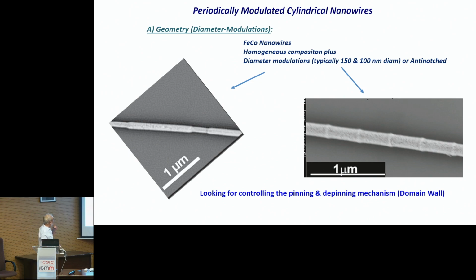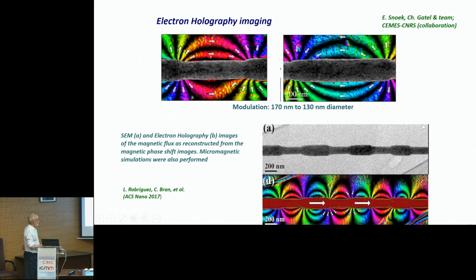Now we go to the last part of the talk, giving some results of the modulations in diameter nanowires. You see these two types of modulations. I like very much this image obtained in Toulouse. You see, this is a nanowire with a thin region of the diameter between two large diameter segments. So these colorful regions correspond to the induction magnetic field outside the nanowire. So we are observing the lines of magnetic field outside the nanowire. You see that in the transition of diameter, we can observe that there is accumulation of magnetic charges generating the field outside.